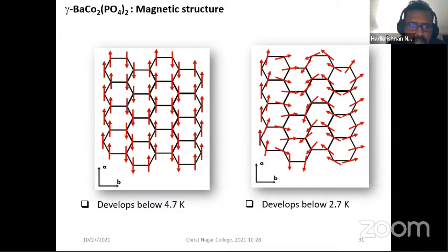On the left-hand side, if you look along the a-axis, it's one line of arrows pointing up, the next line pointing down, then again pointing up. That's the collinear order. And on the right-hand side, you would have completely helical order. It's a helix. It's a non-collinear order. It's not along a line, but it's in the plane. So this compound has two magnetic domains, and these two domains coexist.